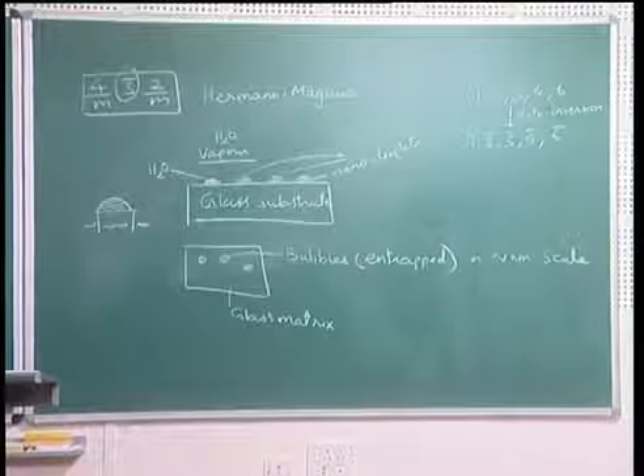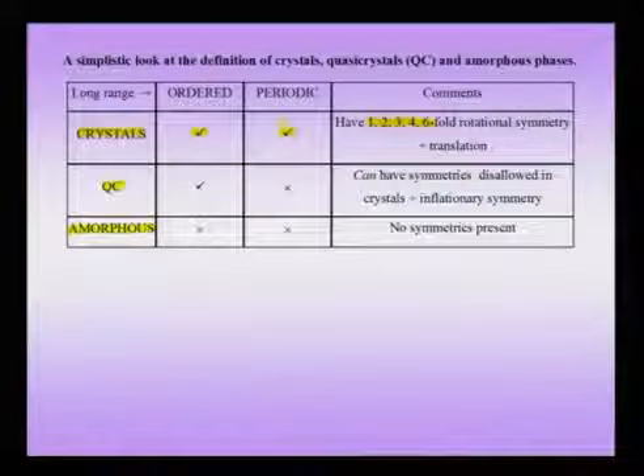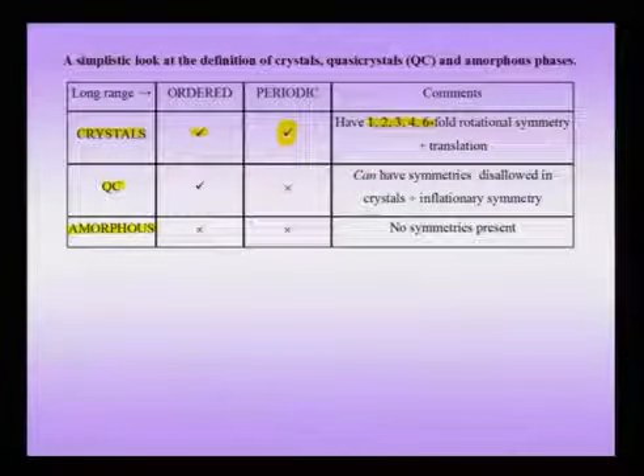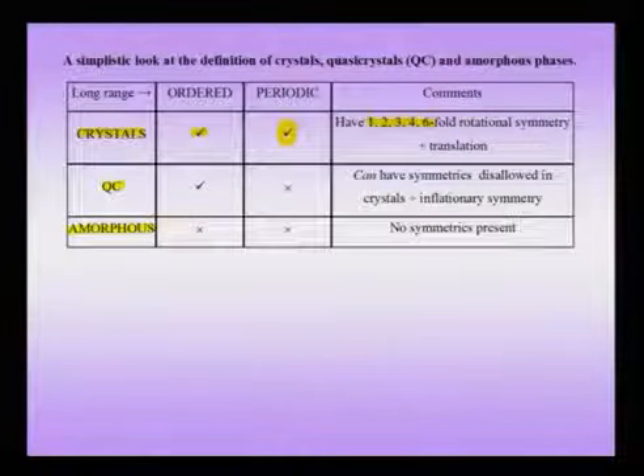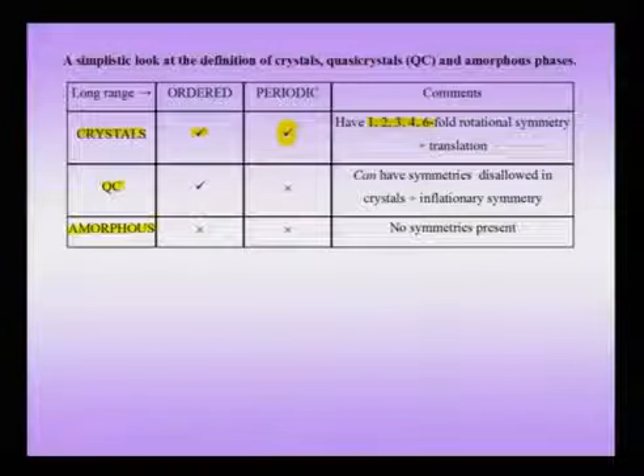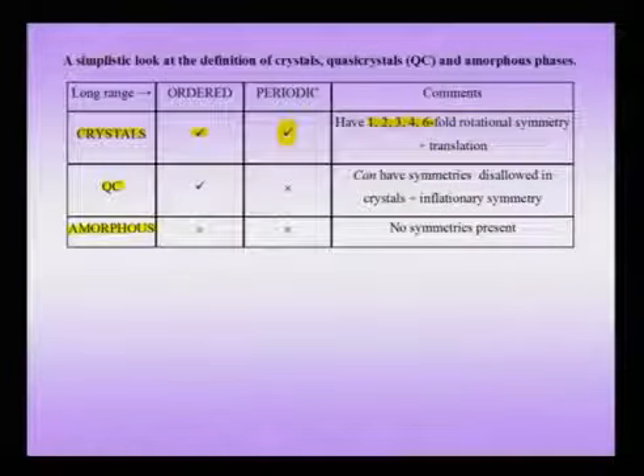Nevertheless, the presence or absence of these symmetries is not going to destroy a crystal, but the absence of translational symmetry is definitely going to destroy a crystal, and this translational symmetry has otherwise been called the periodicity of a crystal. Typically crystals are periodic in all three dimensions, but we can also think of crystals in lower dimensions, like a graphene sheet, which can be thought of as a crystal in 2 dimensions. Therefore, crystals are those which at least have translational symmetry, but typically have higher symmetries, which include rotational symmetries like the 2-fold, the 3-fold, the 4-fold and the 6-fold.